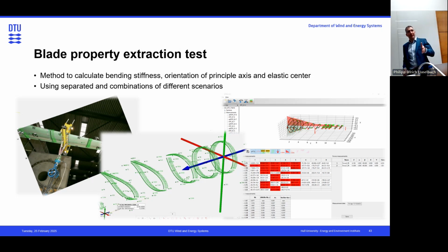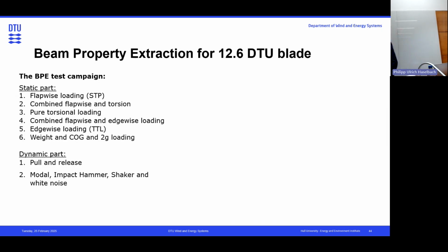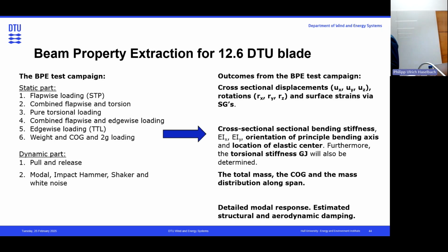And usually we have different cross sections with markers, and then we have different load cases where, for the static test, we usually have 5 to 6 load cases where we load it in flatwise, edgewise, in combination, and torsion and so on. And from the blade response, we can extract basically the cross-sectional displacements and rotations, and we have the surface strain that we can measure. And then based on the mathematical approach behind it, we can derive the stiffnesses, the torsional stiffness, and so on, and compare that to our numerical models. And that will be published very soon. I just need a few more days to finish the article, I think, and then it will be out there.